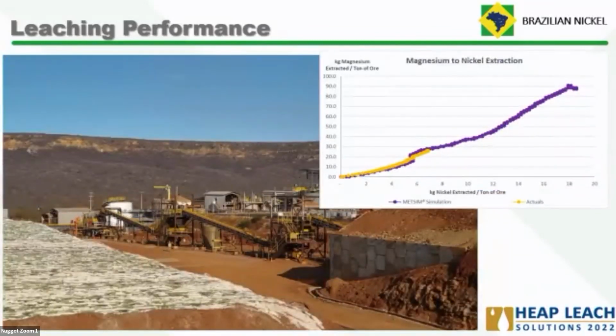Another great chart is presenting the kilograms of magnesium versus the kilograms of nickel extracted. Really great correlation. And since our approach to heap leach is all based on acid availability, this is how we control it. So if we can guarantee that we maintain control of this ratio in terms of extraction, we know that we're going to achieve the ultimate extraction that we carry.